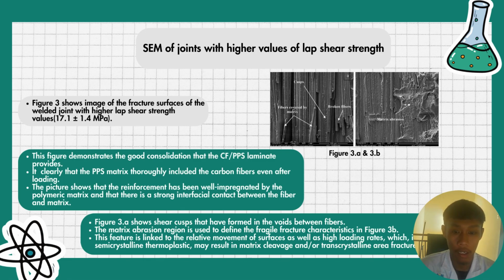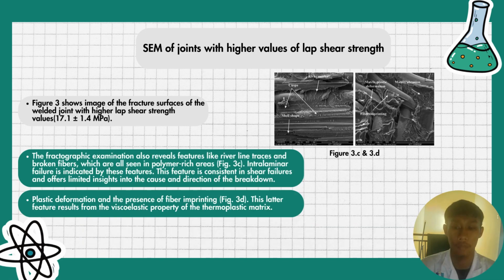Figure 3a shows shear cusps that have formed in the voids between fibers. The matrix abrasion region is used to define the fragile fracture characteristic shown in figure 3b. This feature is linked to the relative movement of surfaces as well as high loading rates, which in the case of semi-crystalline thermoplastic may result in matrix cleavage or transcrystalline area fracture. The fractographic examination also reveals features like river line traces and broken fibers, which are all seen in polymeric areas in figure 3c. Intralaminar failure is indicated by these features. These features are consistent in shear failures and offer limited insight into the cause and direction of the breakdown.